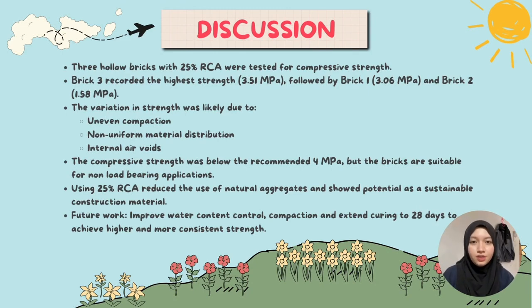3 hollow bricks with 25% RCA were tested for compressive strength. Brick 3 recorded the highest strength, 3.51 MPa, followed by Brick 1, 3.06 MPa, and Brick 2, 1.58 MPa. The variation in strength was likely due to uneven compaction, non-uniform material distribution, and internal air voids. The compressive strength was below the recommended 4 MPa, but the bricks are suitable for non-load bearing applications. Using 25% RCA reduced the use of natural aggregate and shows potential as a sustainable construction material. Future work: improve water content control and compaction, and extend curing to 28 days to achieve higher and more consistent strength.